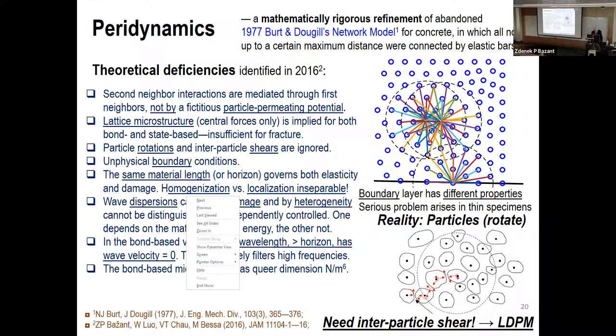What is the main problem in reality? You don't have particle-to-particle potentials above the atomic scale. For example, in reality, there are some material particles. A central particle is connected to a boundary particle not by a potential directly, but through intermediate particles. And an important point is that they rotate and have shear. So shear is very important actually. And that's a different behavior, which is actually the basis of another model, LDPM, developed at Northwestern by Cusatis.